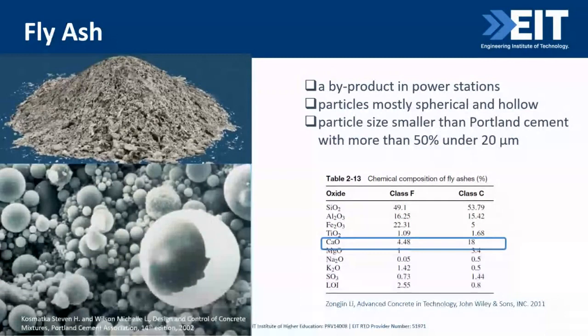The particle sizes in fly ash vary from less than 1 micrometer to more than 100 micrometers, with their average size measuring less than 20 micrometers. Okay, fly ash can be, as shown here in this table, categorized into two types based on the types of coal burnt according to ASTM standard. So we can see Class F fly ash contains less than 10% calcium oxide, and Class C fly ash actually contains about 15 to 30% of calcium oxide. Okay, so they can be called low calcium fly ash and high calcium fly ash respectively.